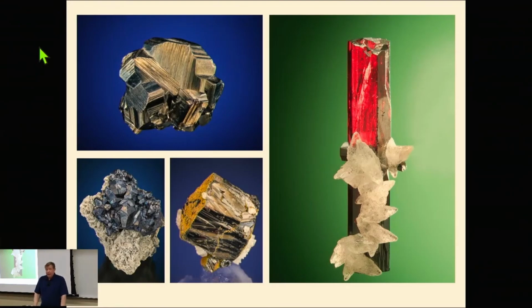Pyrargyrite usually has a much darker color, and that's because the antimony bond back to the sulfur is stronger and shorter. So the color from proustite and pyrargyrite is what we call a semiconductor band color. Light comes in, it excites the bonds, and you get a color depending on where these bonds have a particular energy length. For the arsenic, it gives you that very, very red color, meaning that's the only color it didn't absorb. For the antimony, it's usually darker.